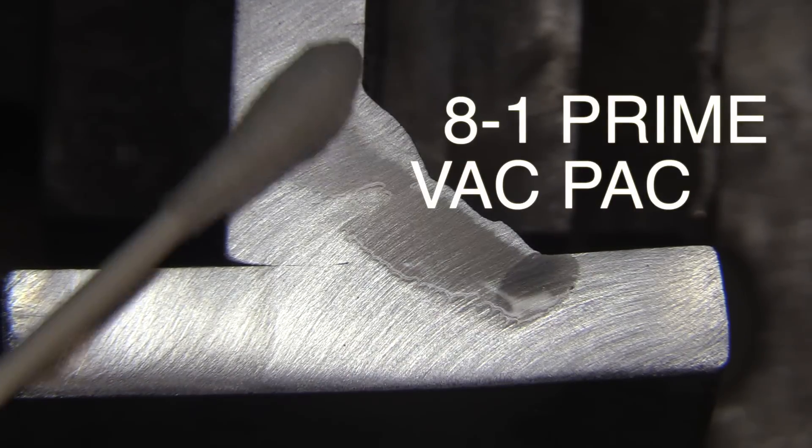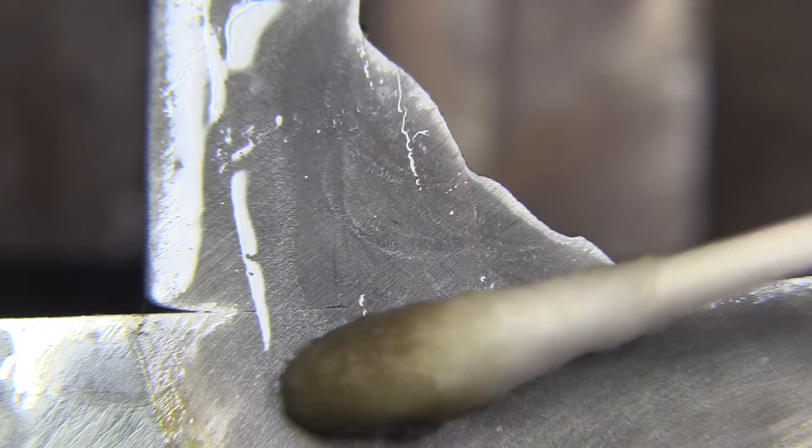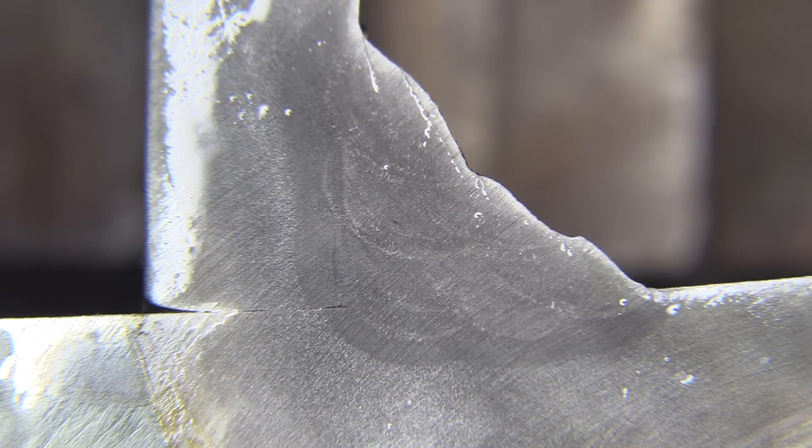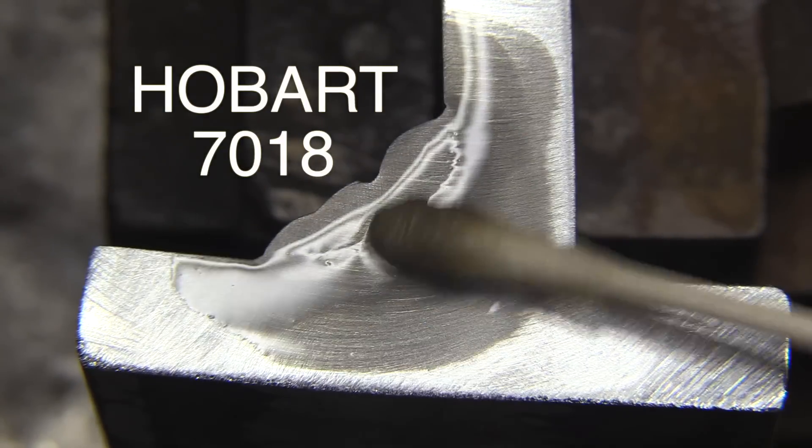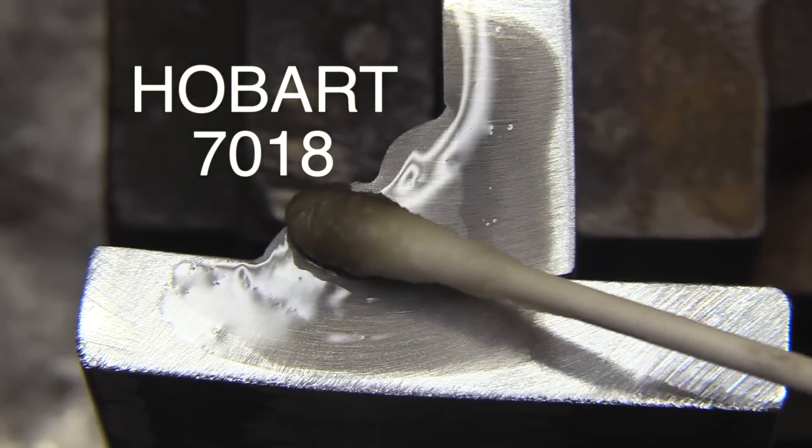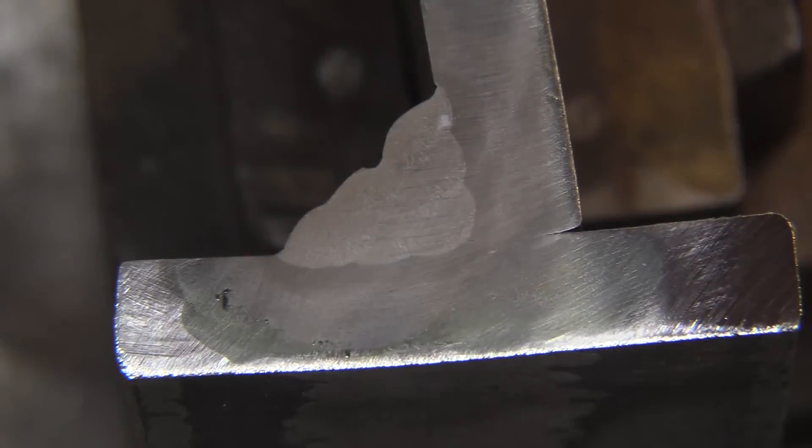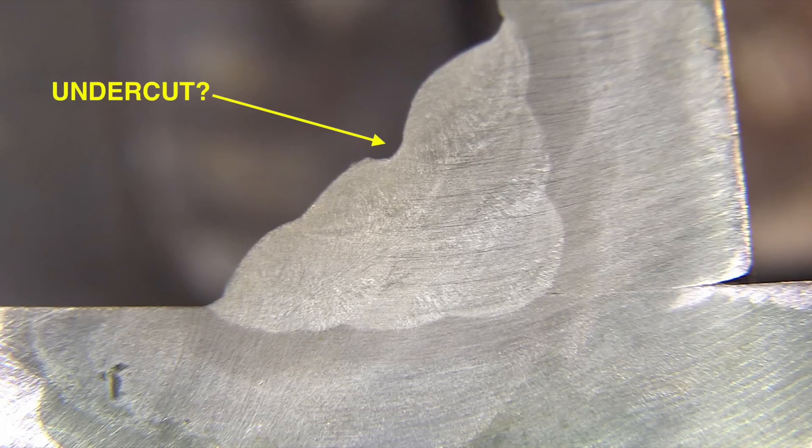I'm using a solution, an etching solution that's designed for passivating stainless steel and removing heat tint from stainless steel, but it really brings out the weld nugget on this carbon steel. All right, that's the ESAB. And here is the Hobart. You can see I slipped. It looks like I shook a little bit and didn't pause to fill it up. I got a little bit of bead on bead undercut there, or maybe I just didn't place the bead exactly where I needed to. But anyway, it's a little distinct low spot there on the face.